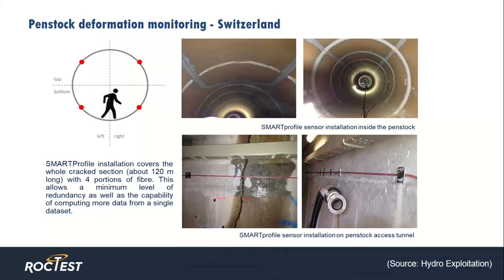Okay, in terms of site coverage, like I said, about 120 meters of smart profile was installed. And due to the flexible nature of this cable, a loop configuration was installed. You can see that here clearly at the top left photo, looped back on itself. Here on the graphic on the left, you'll see the precise location on the tunnel itself of all four runs. And because it was looped, it's one continuous strand of fiber with no necessity for splicing.